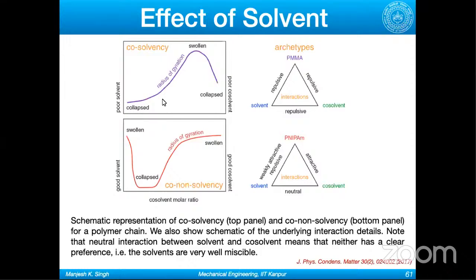The top one is what we call co-solvency. On both sides, you have poor solvent. So this curve basically tells you the swelling, or the thickness of the polymer brushes. As you have pure bad solvent on both sides, you have a collapsed state, but as you mix them at a certain ratio, they swell and form a brush-like structure.